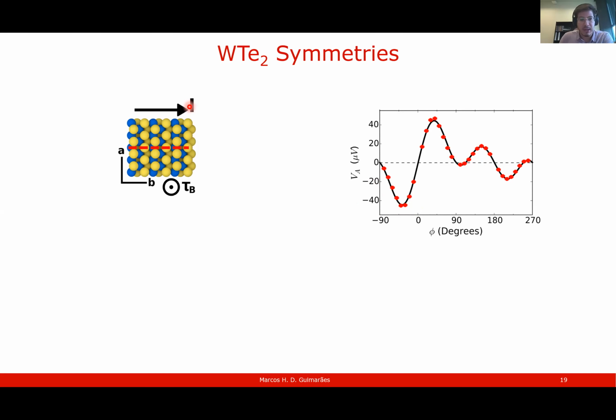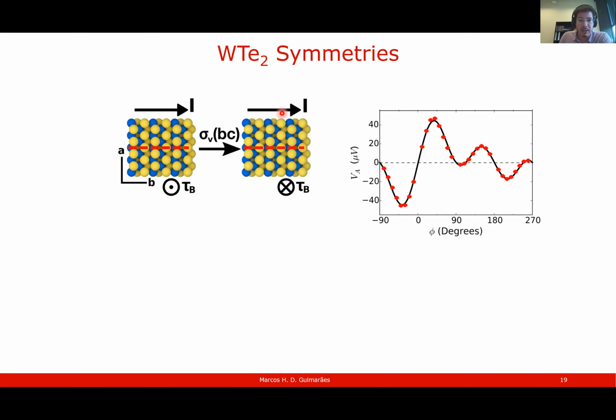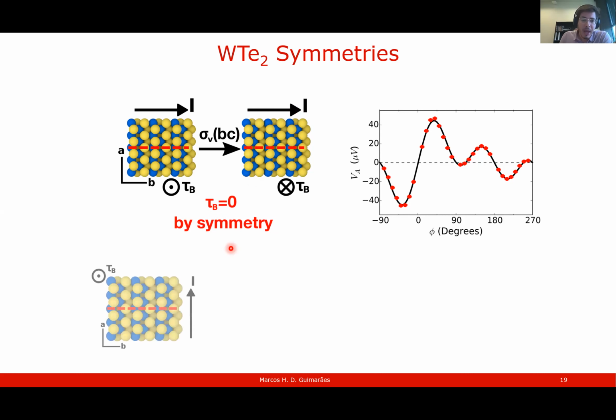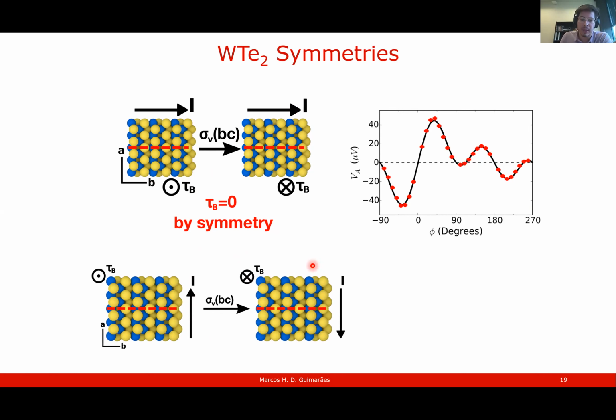And now let's look at the symmetries of the crystal with the torque included. So we have the current flowing parallel to this mirror plane, and let's say that it causes a torque that points out of the plane here. Now, if you apply the mirror plane, the current stays the same, but the torque is a pseudovector, so it has to reverse sign upon a mirror plane. And since the torque is linear in current, this tells you that the torque has to be zero by symmetry. However, if we apply the current perpendicular to this mirror plane, when we apply this mirror plane, we reverse both the torque and the current. So what symmetry analysis tells you is that a torque pointing out of the plane is allowed. It doesn't tell you if it is present, it only tells you that it is allowed.